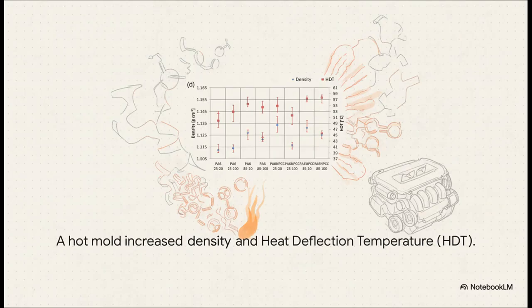And the hot mold delivered 2 more big wins. It bumped up the plastic's density, which means the polymer chains pack themselves together more tightly. And maybe most importantly, it seriously raised that heat deflection temperature. Those higher red squares mean this new and improved plastic can now survive in much hotter environments without warping, like, say, under the hood of a car.